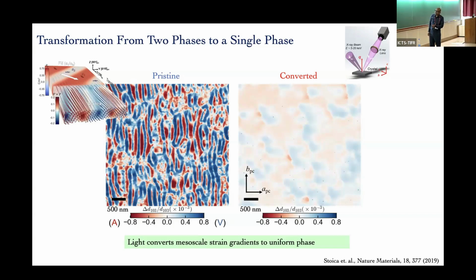This is the vortex, which is the blue part. All this blue is all these little vortices if you zoomed in. This is zoomed out a bit. And all this red phase is the standard, what we call regular A1, A2 ferroelectrics. They're in-plane ferroelectric domains. So one are these vortices, the other look like that. It's a mishmash, okay? You hit it with one single pulse packed with charge, right? It's very important to be above the gap. And boom, all the strain contrast is now practically zero.